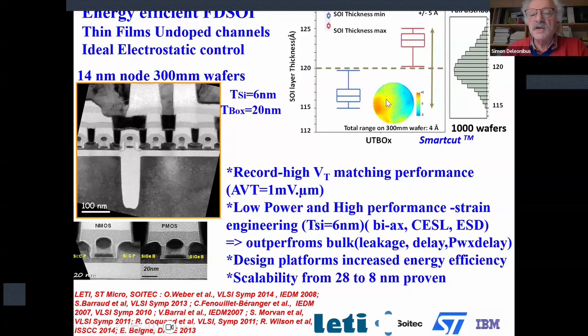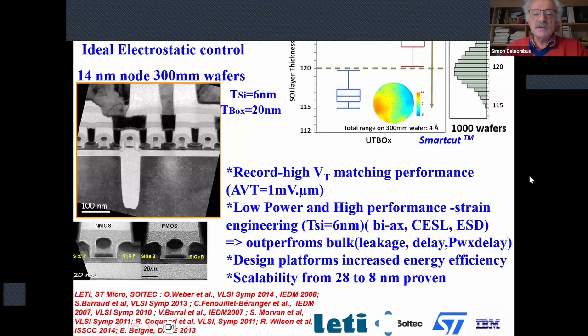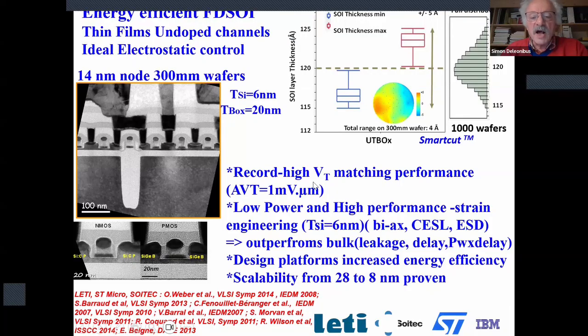Here you can see some statistics made on the film thickness after fabrication, and of course, there's some film consumption during the process, and you can see that the range of max to min thickness is quite manageable. These technologies have been shown to have a record high VT matching performance. I just invite you to look at all these publications I mentioned at the bottom here. And this is a matching parameter, Pelgrom parameter.